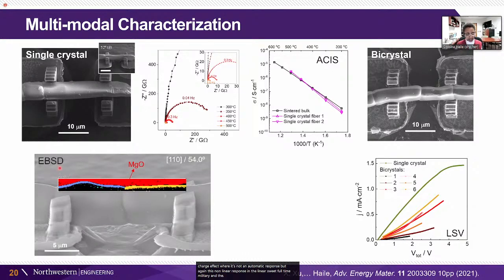And using the electron backscatter diffraction, we are probing here the grain-to-grain orientation. This is a little bit like an Escher picture, a little bit hard to see. This is the underneath part of this crystal. So this is the platform on which it's sort of supported down here. This is the bicrystal sort of floating. These are the orientations now of the two different crystals. We can get the orientational relationship between the two of them. And underneath here is the magnesium oxide support that this whole platform is sitting on. So that's the red region. The key is that we can see these two different crystals that make up this bicrystal, and we can get their orientation relationship between the two of them.